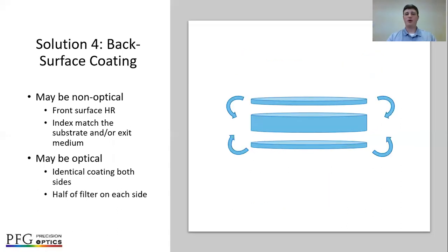Another option is to employ a back surface coating, that is, to coat both sides of the optic so that the stresses counterbalance and maintain flatness. This is oftentimes done for anti-reflective coatings. Both sides of the optic are coated with the same coating. However, you can also do this with high reflective and filter coatings. For example, you can take part of a filter and put it on one side and take another part of a filter and put it on the other side such that their stresses counterbalance. You have to be careful, though, that doing this doesn't introduce unwanted ghost images into the optical system.